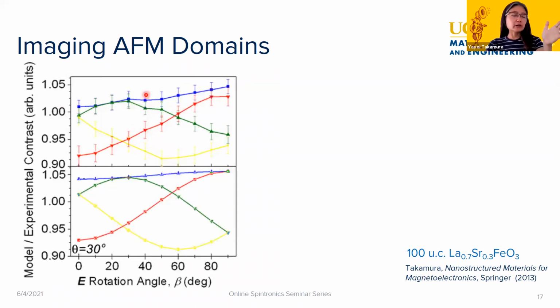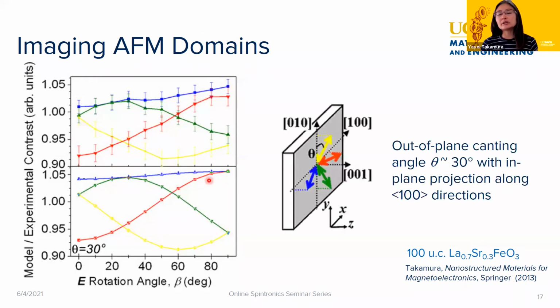what the intensity of each region is, basically pixel by pixel. We can then categorize them into different types of domains, right? And that's what we have here. What we find is that for all the pixels in those images, we can bin them into 4 different types, right? And so they have these different functions as a function of the beta angle. We can compare them to that cosine squared dependence. And so what we can then determine is that in this case, what we have are 4 different types of antiferromagnetic domains, which differ in the orientation of the spin axis.